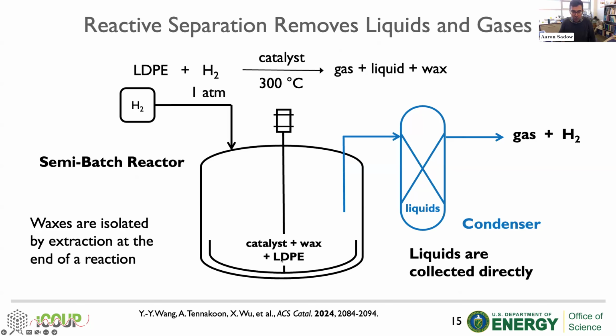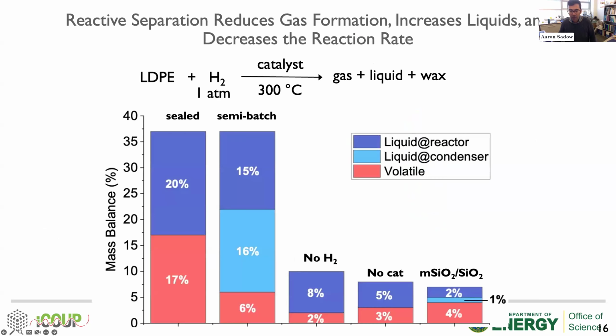The studies I've told you about up until this point would be a sealed batch reactor, where you have the catalyst, the polymer, the products, they're all contained within the same reactor, and it's sealed and heated for some period of time. What we've done in this semi-batch reactor is we allow the hydrogen to flow in, and then anything that has sufficient volatility, just a little vapor pressure, can get transported out of the reaction mixture and end up collected now in this condenser. And so that has a pretty significant effect on how the reaction's performed.